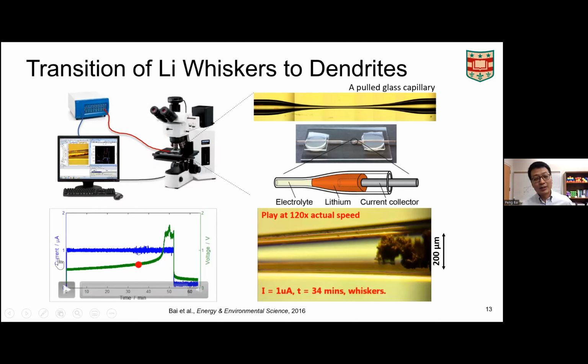You can see that we do the observation while we are still applying the current to the system. So we are applying a constant current to this little capillary cell, and we monitor the voltage, which we represent by this green curve. And at the same time, we check the morphology changes. So you can see here, after about 34 minutes, we already grew some very, very rough structure. It is actually a collection of the whiskers we just saw. But because we know a little bit more about the science, we want to wait, okay? And there's something surprising that will occur.